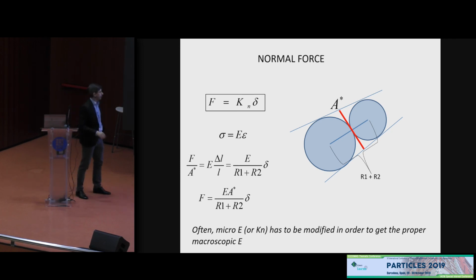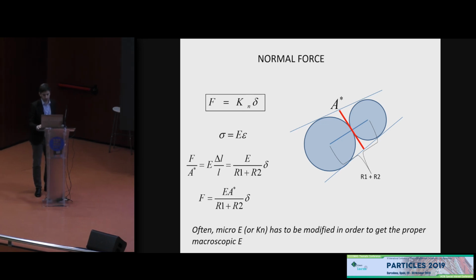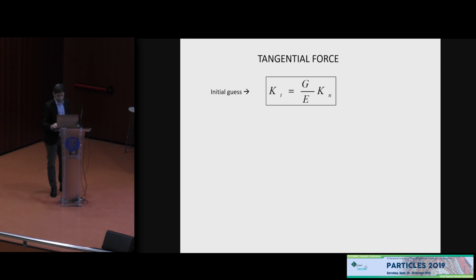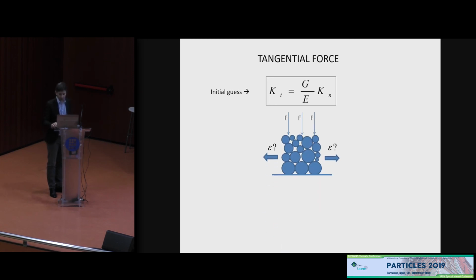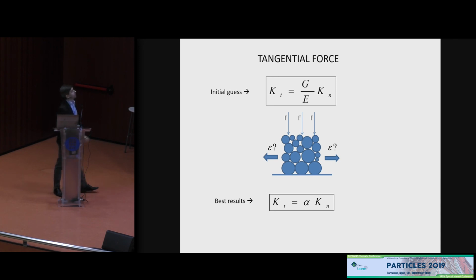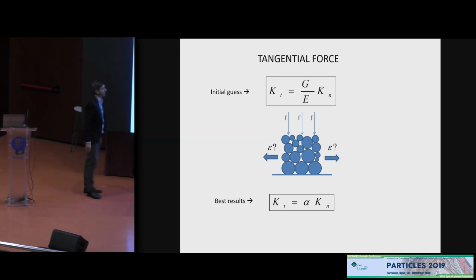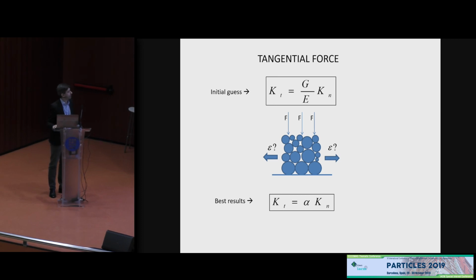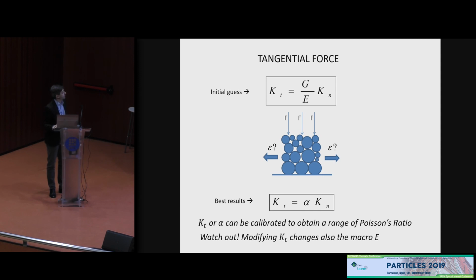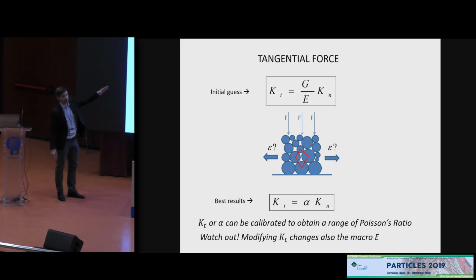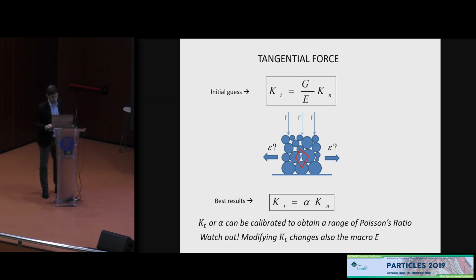Very often, you need to modify the Young's modulus, or if you're using a normal stiffness, to get the proper macroscopic Young's modulus. And what about the tangential force? Well, the first guess would be to use a tangential stiffness, which is the ratio between the shear modulus and the Young's modulus times the normal stiffness. But when you have a random packing, for example, and measure the lateral strain, best results are not obtained for that expression, but for other expressions where you have to adapt a coefficient a little bit, and then you finally get the correct Poisson's ratio. Watch out, because modifying the tangential stiffness can also change the elastic modulus, because there is some vertical component of the tangential forces, and then you're modifying the vertical stiffness. So that's dangerous.